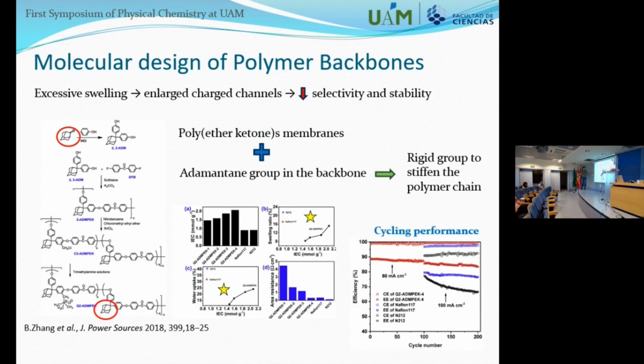And when they do the cycling performance, they obtain very good results. The results are the Coulombic efficiency and the energy efficiency, and they compare with some Nafion membranes up to 200 cycles, and they see that both the Coulombic and the energy efficiencies are better than these Nafion membranes. So they have effectively improved the barrier properties for electrolytes, but they are also not losing that much conductivity, because otherwise the energy density would be lower.